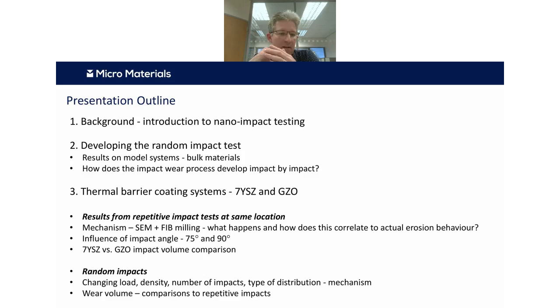As well as SEM, we can do some focused ion beam milling to look at the subsurface damage, and we can see how well the impact test correlates with the actual erosion behavior. And we can also look at things like the effective impact angle and also the comparison between these two different thermal barrier coatings.